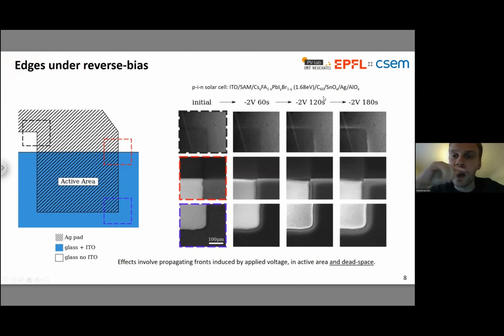So one potential cause of edge effects you've always got to worry about is, does the loss of encapsulation at the edge of my boundary maybe allow things to escape or other things to come in? But we took quite strong precautions in this work to make sure that that's not what's going on. We also tested these cells in inert gas environments.